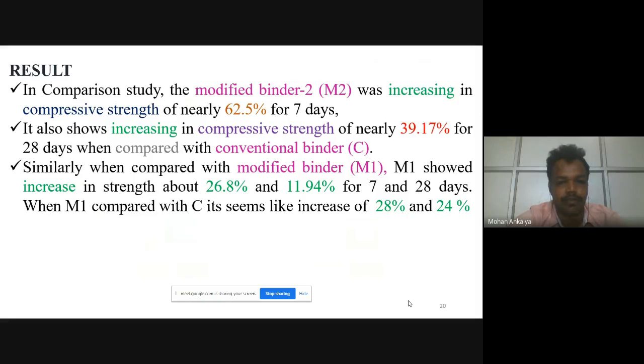In comparison, the modified binder 2 was found to be increased nearly 62.5% for 7 days. It also shows an increase in compressive strength of 39.4% when compared with the conventional binder. Similarly, modified binder 1 showed an increase in strength of 28.8% and 11.4% for 7 and 28 days when compared with the conventional binder.